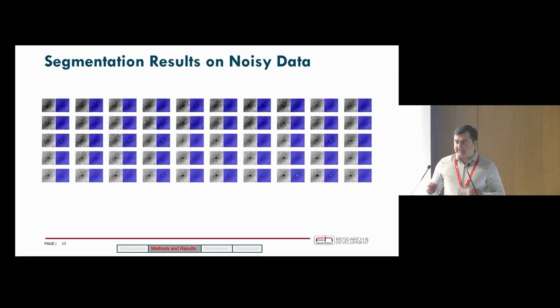Again, we applied the same model, this time on extremely noisy data, but we know we defined these defects and we know all of the characteristics of the defects. When we add the noise, in some cases visually it's impossible to distinguish whether there's a defect or not, but the trained algorithm was actually able to segment really small ones, especially that one, and most of them performed well.